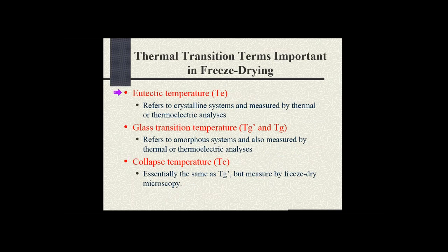Now, these are important because we know where ice melts. Ice is going to melt once you exceed 0 degrees Celsius. But the interstitial space, whether it's got a eutectic or a glassy phase, those are very different temperatures. And again, this is something that we're trying to identify through the use of these tools, including the freeze-dry microscope.